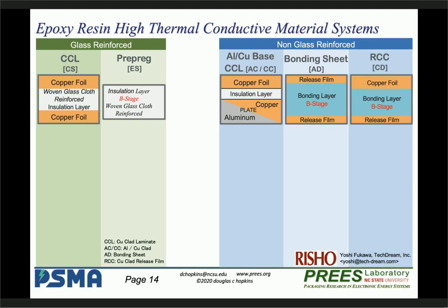Well, the last one would be your typical copper on polymer, copper on polyimide, copper on organic epoxy. It's copper foil bonded to your B-stage material, which is your insulating layer. And then you can pattern this and stack these up. You can pattern this and stack it onto the IMS so you can get multi-layering. You can use this for embedding. You can put in the bonding layers, the center one, as fillers between if you need, or it can actually squish down depending on how hard you want to press it. So this is a system now that allows us to do, again, multi-layered substrates, moving towards embedded components.